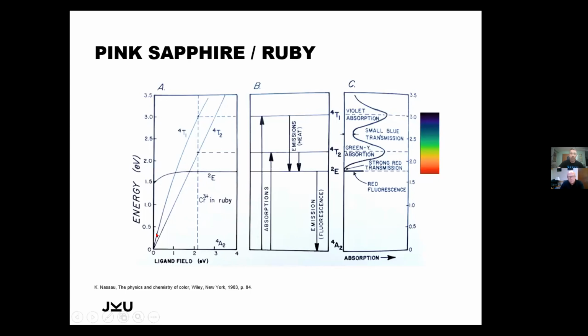So these chromium energy levels are here represented by these lines. We have 2 different lines here for the 2 different term shapes, which I don't go into details because I think this would lead way too much into the physics. But you see that these lines depend on the strength of the ligand field that you have, and there is a value assigned. So when we cross here the ligand field of the chromium in a ruby, we see that the 4T2 level is a little bit above 2.2 electron volt, and we have, if we look here, an absorption. If we go to the second absorption, we are at 4T1, approximately at 3 electron volts, and again we have here the absorption.